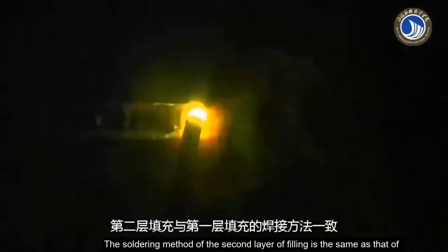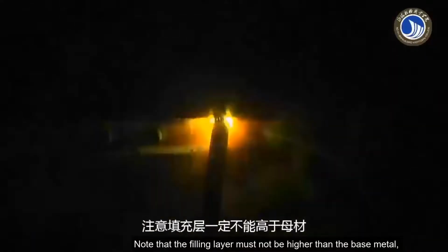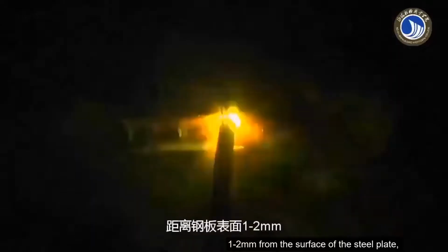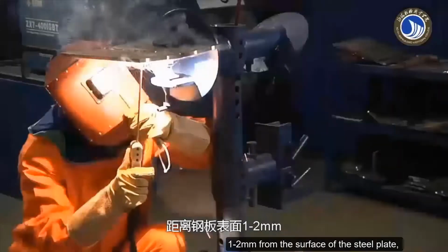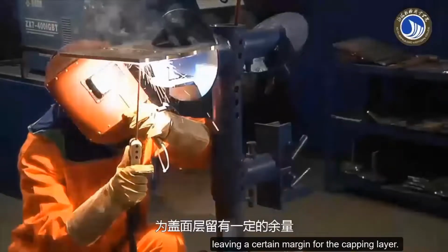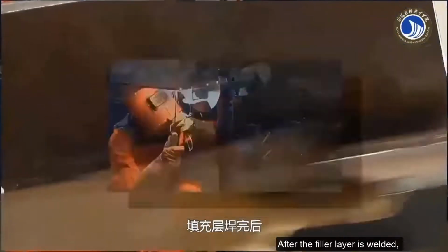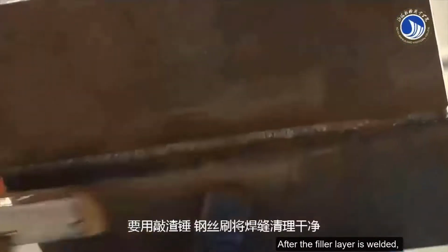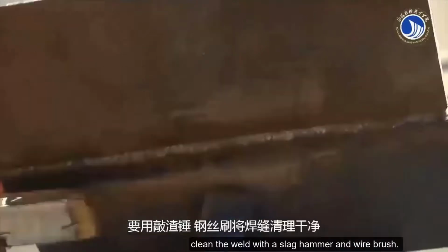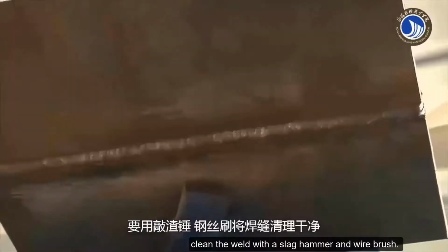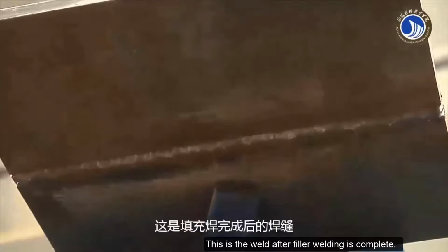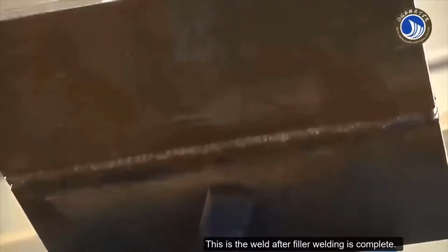The welding method of the second filling layer is the same as that of the first. Note that the filling layer must not be higher than the base metal; keep it 1 to 2 mm from the surface of the steel plate, leaving a certain margin for the capping layer. After the filler layer is welded, clean the weld with a slag hammer and wire brush. This is the weld after filler welding is complete.